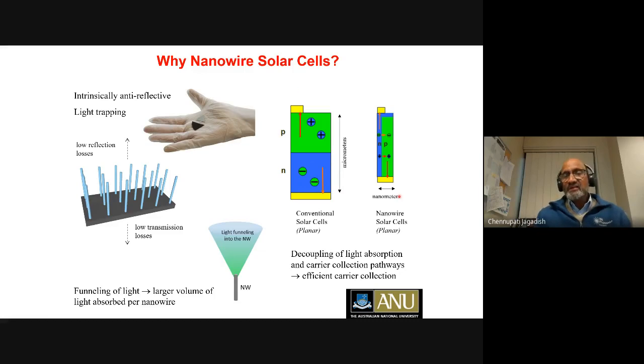But in the case of nanowires, you can make the nanowire as long as you want to absorb the light. You can make a radial p-n junction. That means you get a p-type core, for example, and an n-type shell, or the other way around. Thereby, the light can be absorbed this way and the carriers collected in a 90 degree way. So you're able to efficiently collect the carriers, essentially decoupling light absorption pathways and carrier collection pathways.